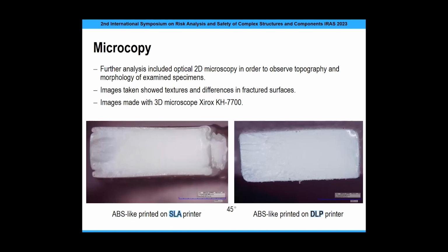A further analysis was conducted with 2D microscopy, and you can see the different topography and morphology of the examined specimens, and also the similarities between them. Because photopolymerization makes very dense and isotropic parts, both fracture surfaces are very dense and isotropic. But here you can see the difference. This is the initial start with low strength, and you can see the shear part of the outer layers start from here, then evolve into this brittle part and end with a ductile part. For the DLP printer, the initiation was like a striation here, and then it evolved into a brittle part and finished.